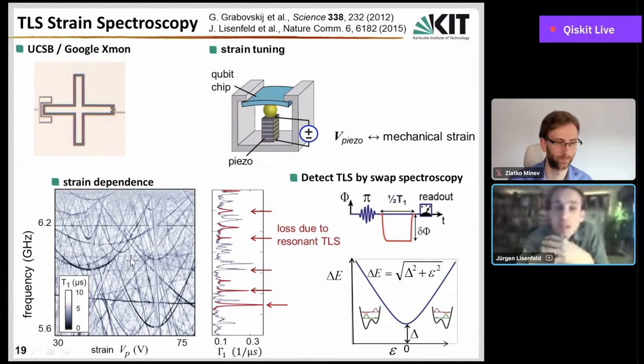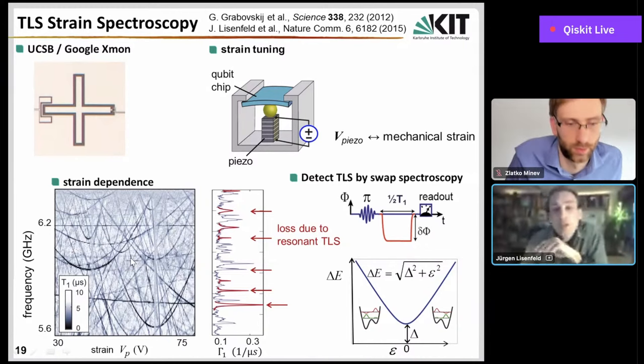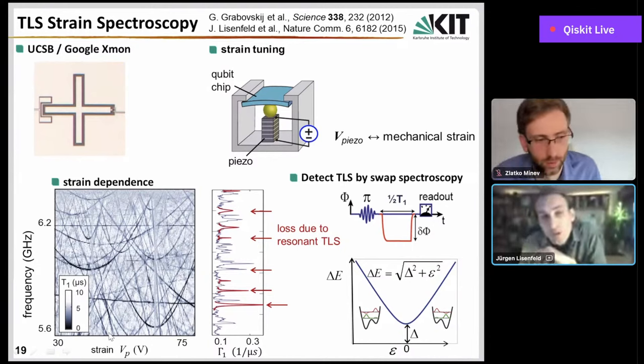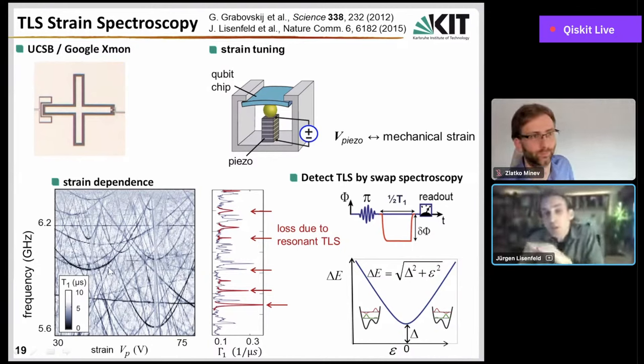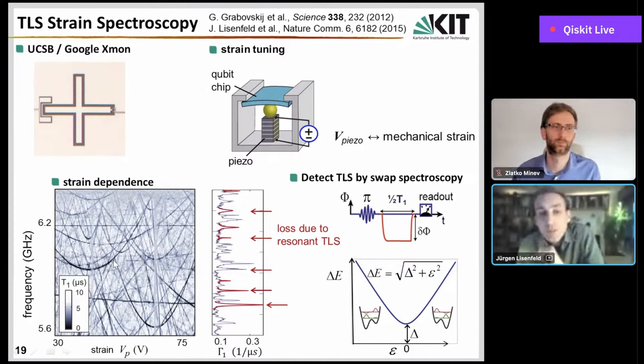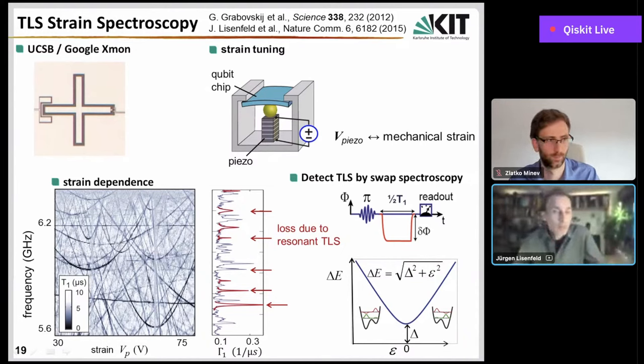In addition, we can say, of course, that, for example, dipole moments and also coupling strengths to strain, which you can also extract from these measurements, are also compatible with measurements obtained on glasses. So in that sense, everything still seems to be compatible with these defects in these qubits being the same that we have in our glasses, or that were studied in the glasses. But this is, of course, not the final word.